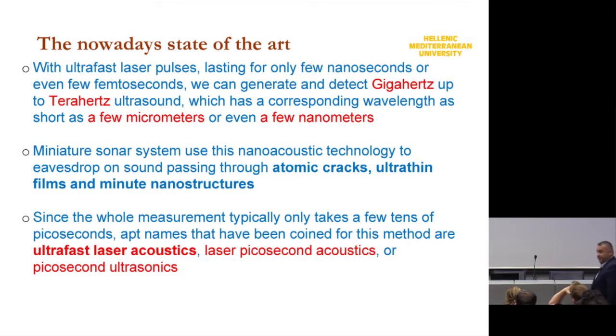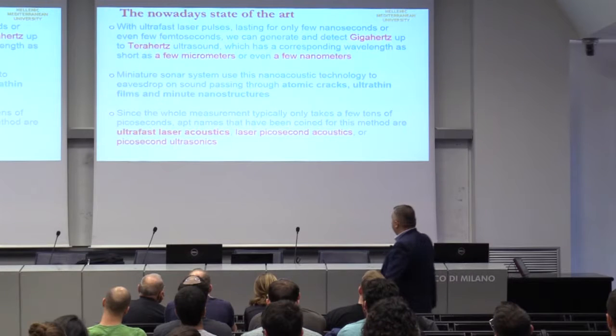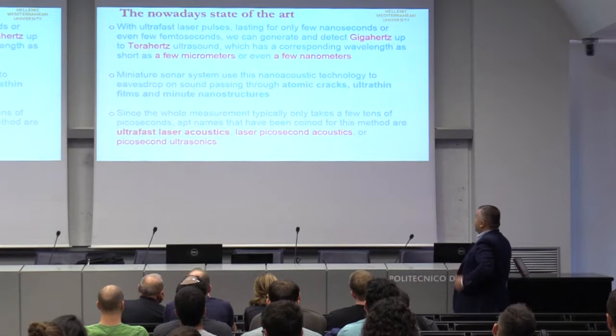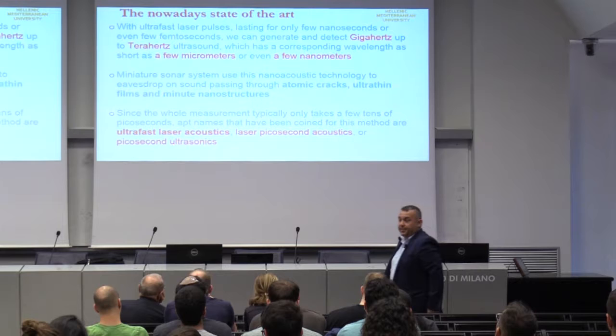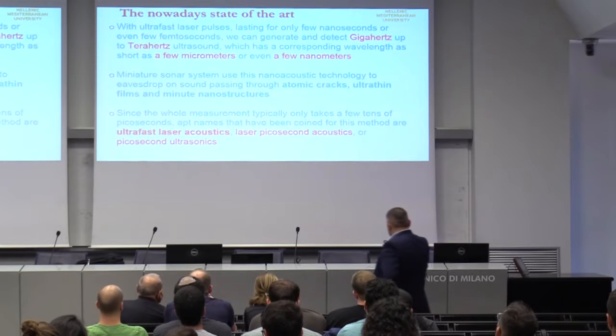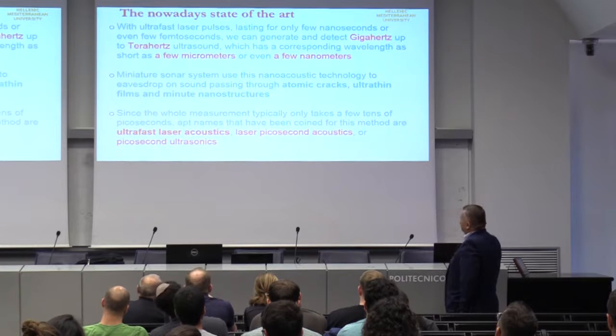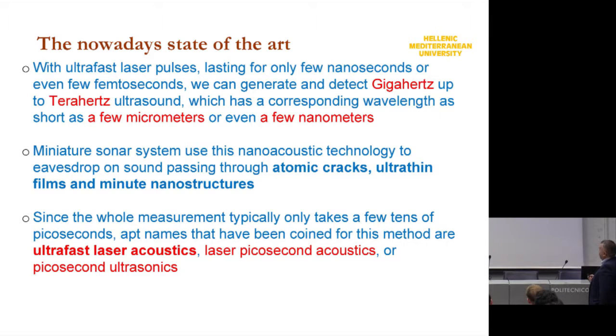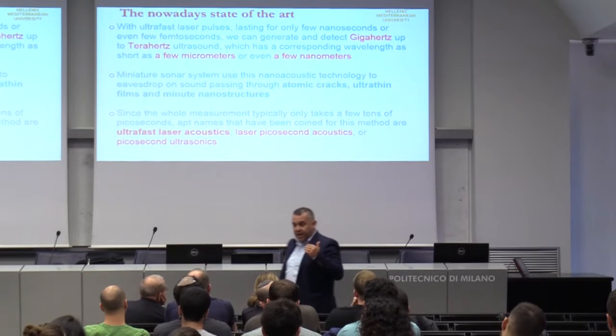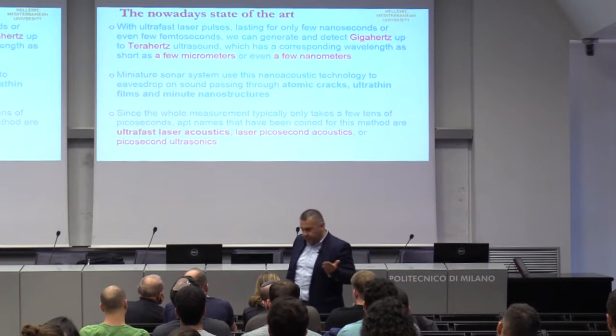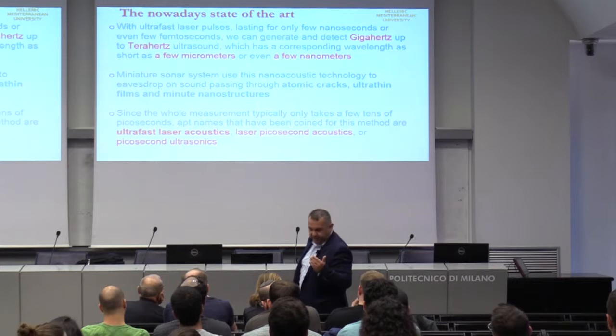Nowadays, the state of the art of this field is with ultrafast femtosecond laser pulses, for example, with which we can generate and detect, of course, mechanical acoustical strains in the order of gigahertz up to terahertz, which correspond in a solid to a mechanical wave that has a wavelength of only a few microns, even a few nanometers. So we have a mechanical strain with the imaging abilities of a soft X-ray or an X-ray pulse.